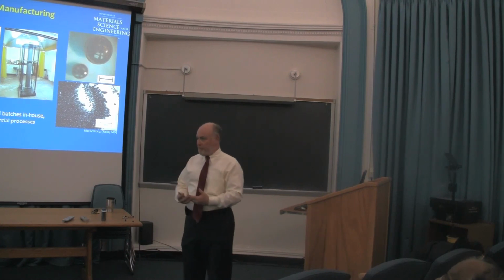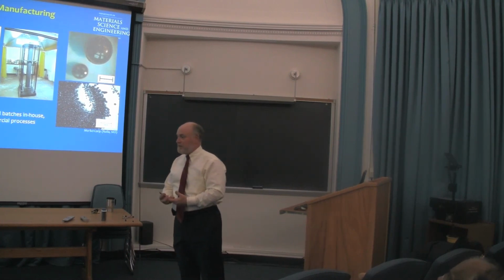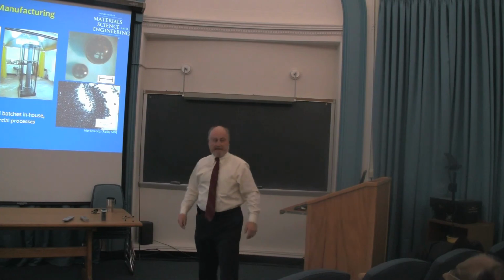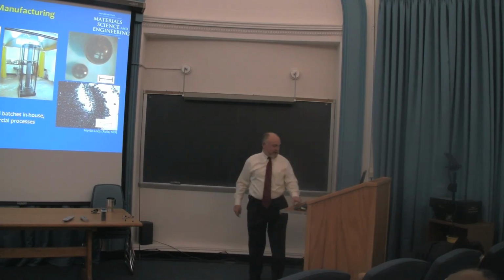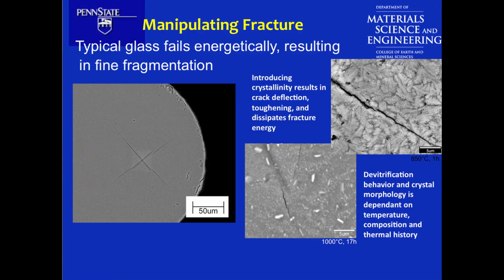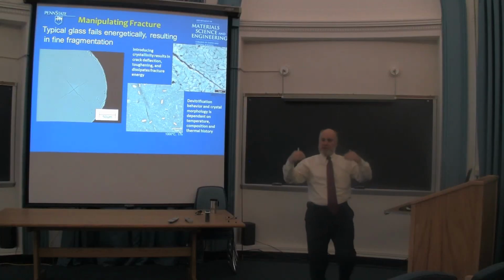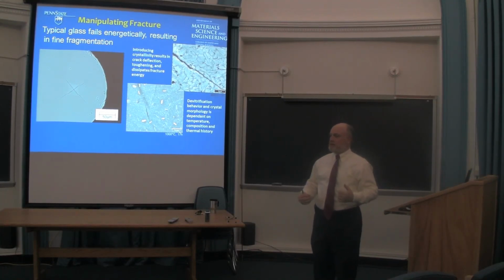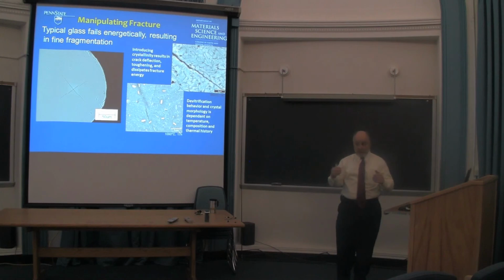We also do work on the fused materials as fused. They're useful for things like the TTT diagrams and whatnot. And that's important because we want to know how the microstructure evolves as a function of temperature and time. What percent transformation of different crystalline phases do we get as a function of heat treatment? And how does it interact with the crack to crack, deflect, and increase fracture toughness? Classical ceramic science. Okay? Classical geochemistry.